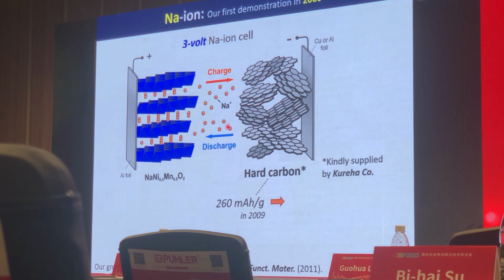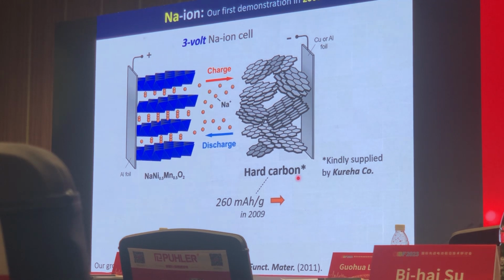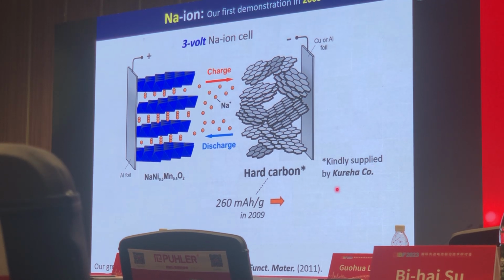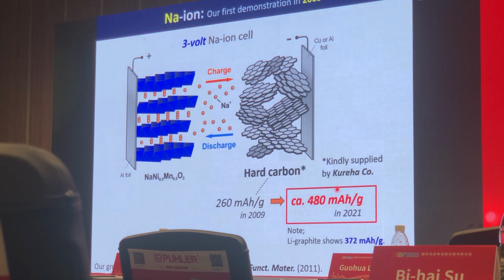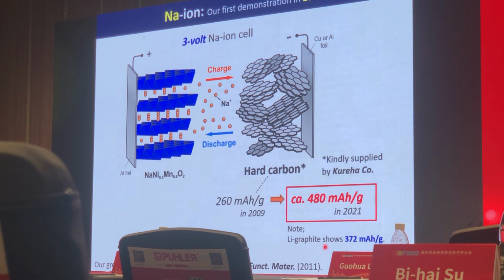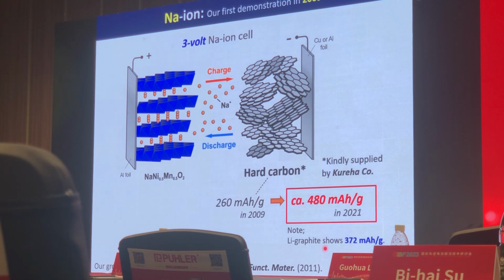In our first demonstration in 2009, the reversible capacity for hard carbon was 260 mAh/g. This time, hard carbon was kindly supplied by Kureha Corporation. But after that, we made an effort to develop higher capacity electrode materials. And finally, 2 years ago, we achieved 480 mAh/g, which should show higher energy density than lithium GIC.